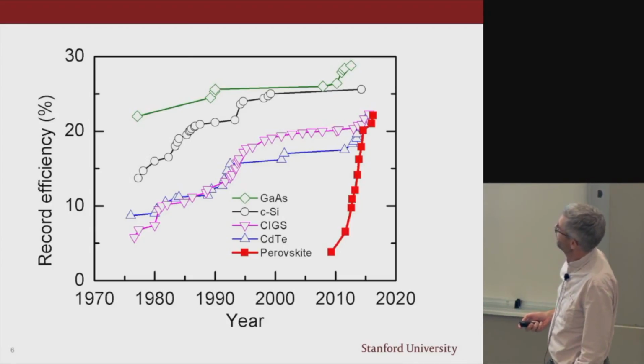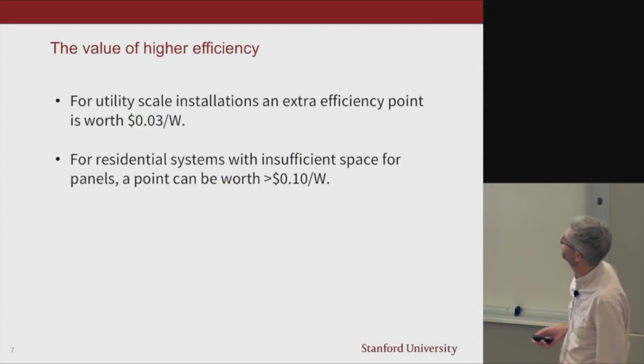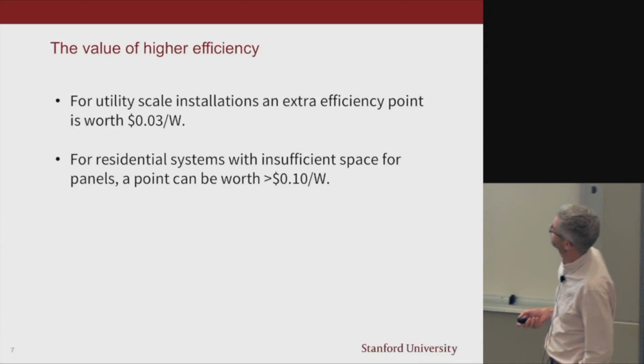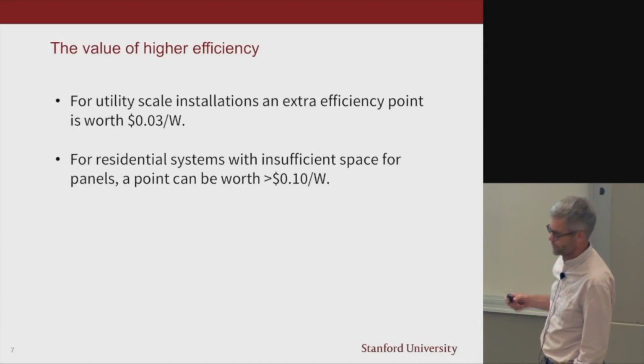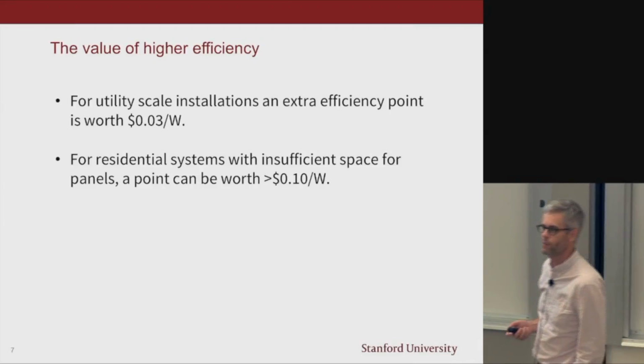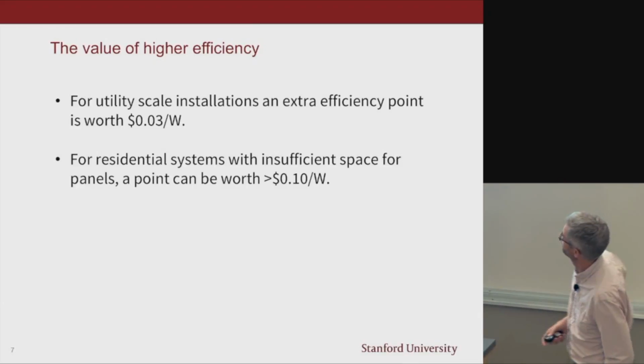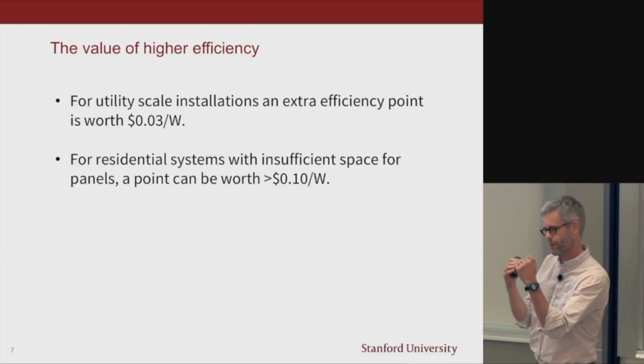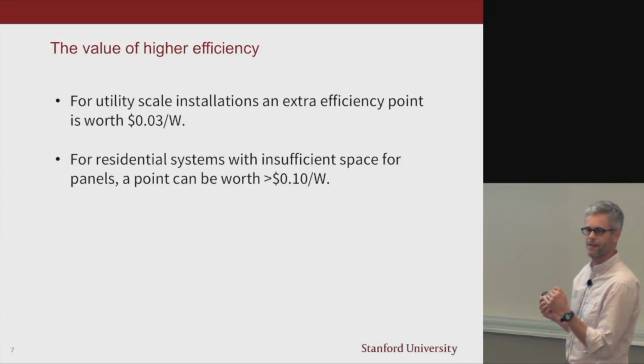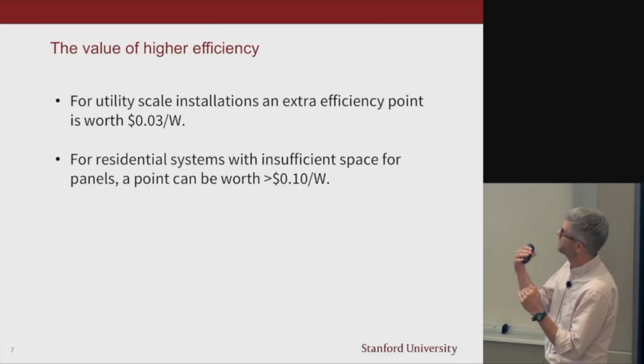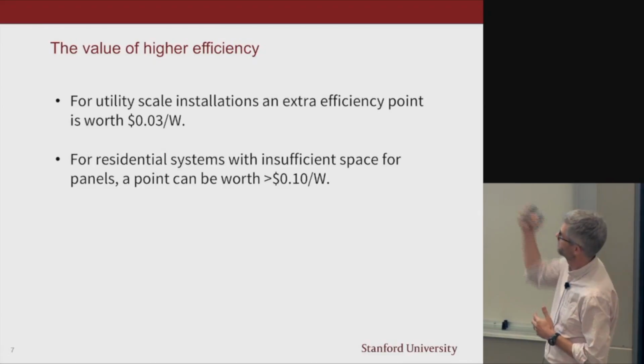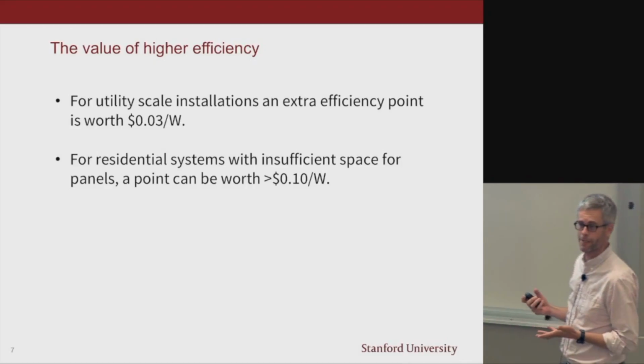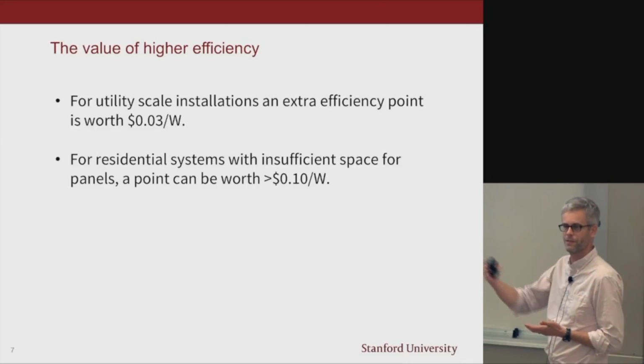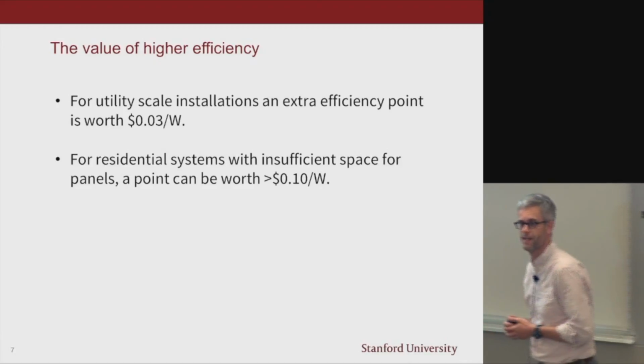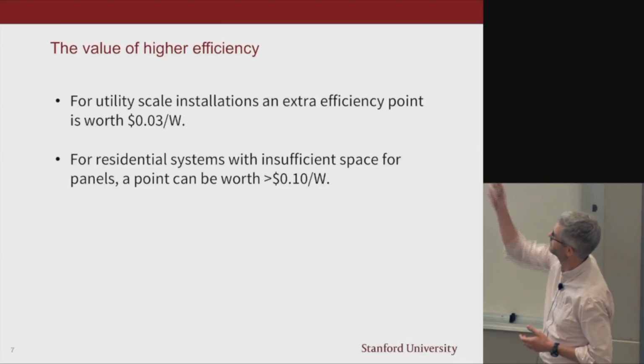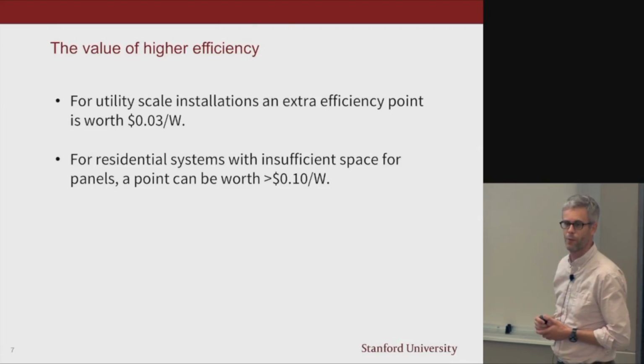But I believe very high efficiency is where things need to go. We've done some calculations, as have other people, and we find that when you can raise the efficiency by 1 point, you improve the value of the module by 3 cents per watt. So in other words, if we can go from 20% efficiency to 25%, instead of paying 50 cents per watt, you should be willing to go up to 65 cents per watt because of all the extra power. And then you can look in the market, and there are products with a range of efficiencies, and you can find out what the selling prices are. Of course, the utility companies know what they're doing, and it indeed is exactly 3 cents per watt